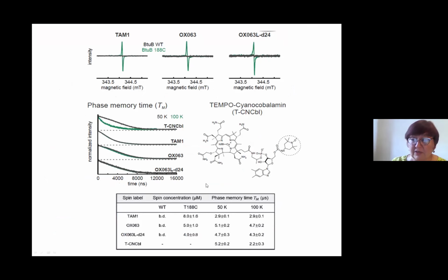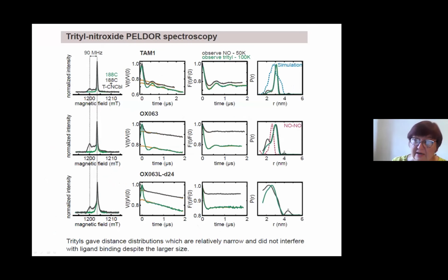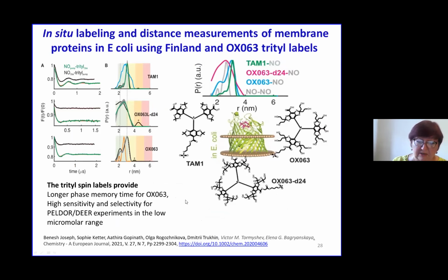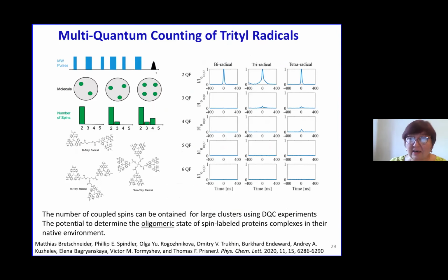Here are results of the investigation of the membrane. You see here quite a narrow line for nitroxide and trityl. So finally we can conclude that trityl spin labels provide the longest phase memory time for OX063, high sensitivity and selectivity for PELDOR experiments, and a low micromolar range. And this is already in cell. So that was quite an interesting thing. Spin labels based on trityl are nice.